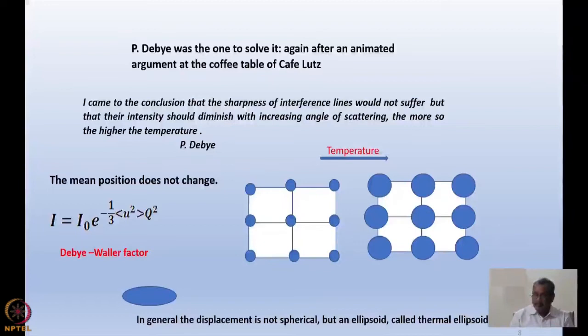When I raise the temperature, it is not that the atoms run away from that place, rather their vibration around the mean position increases. As if the atom is expanding in size with temperature and not running away. From smaller size, the atoms become larger. And if you remember, I told you, the larger the size of the atom, but this is a dynamical effect, the atom is really not becoming larger.